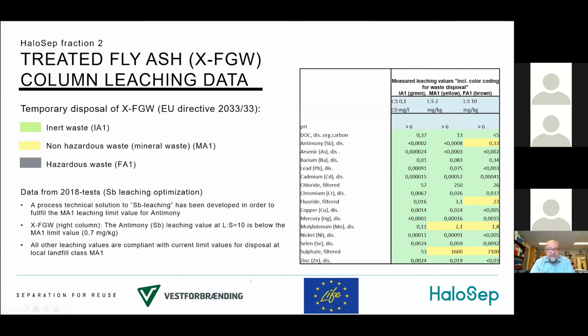Here I show the column leaching data for the treated fly ash. To make a long story short, we now comply with the leaching values for a disposal site class non-hazardous waste. This is shown by the color coding: if the material has a green color, you can place it on an inert waste disposal site. If it's yellow, you have to go to a non-hazardous waste or mineral waste disposal site. And if it's gray, you had to dispose it on a hazardous waste disposal site.